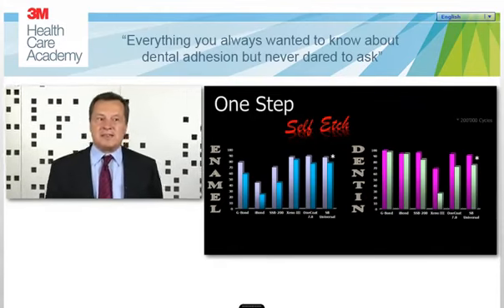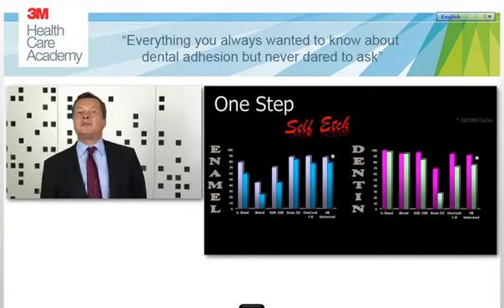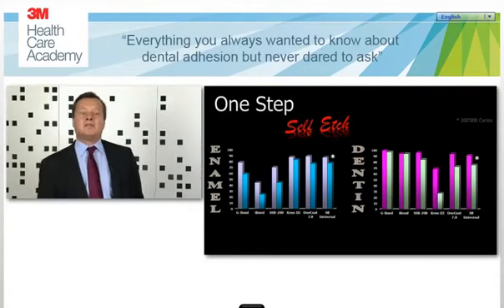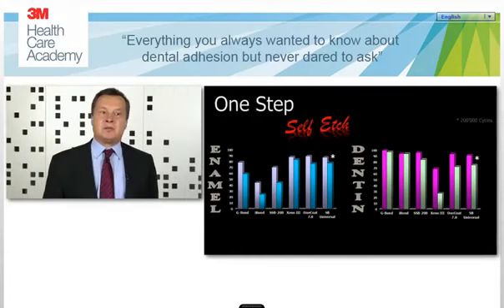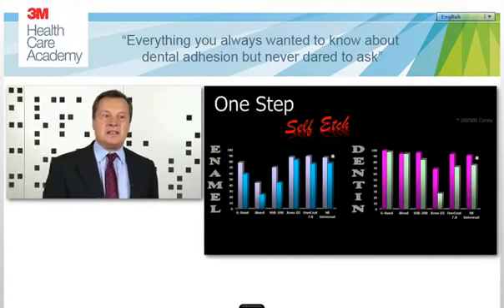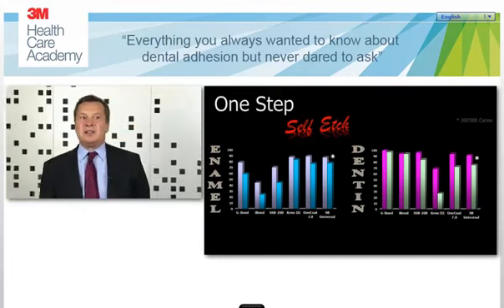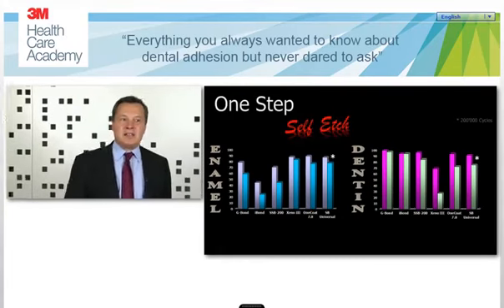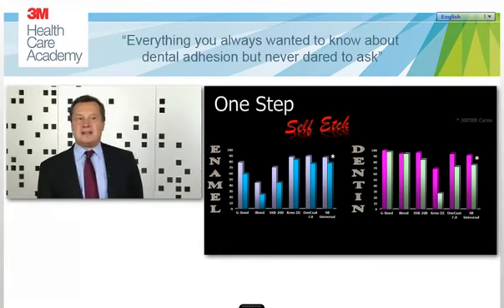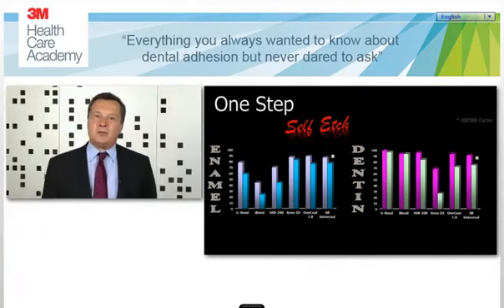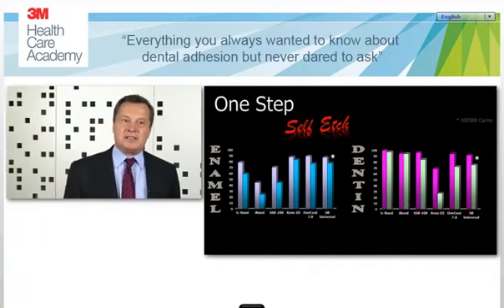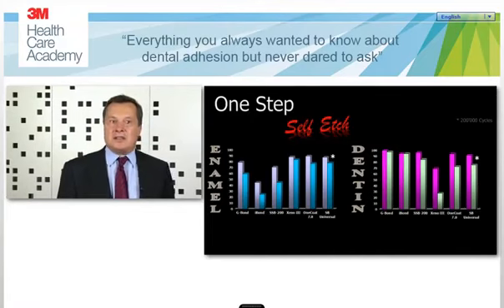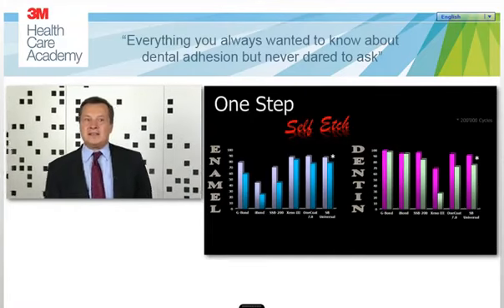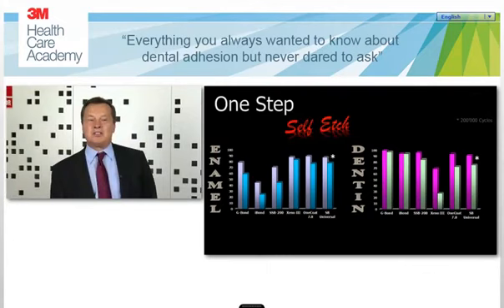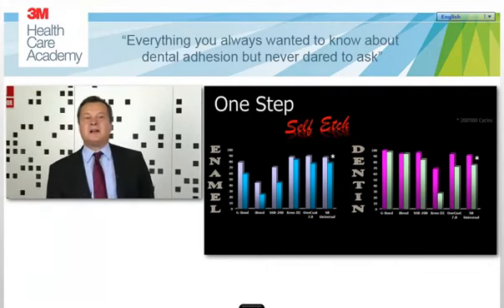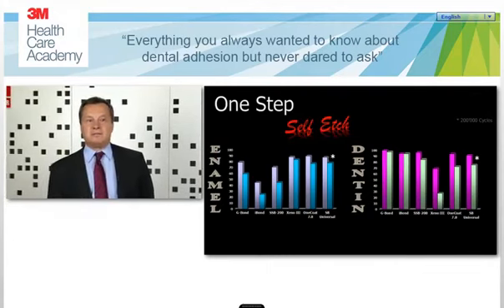And the latest developments go in the direction of universal adhesive systems. One of the first adhesive systems in this field was Scotchbond Universal. You can see that Scotchbond Universal is really very, very good on the enamel side and also on the dentin side. And again, compared with classic three-step adhesive systems, it is at least as good as OptiBond FL, at least in this in vitro evaluation before and after loading under simulation of dental fluid.